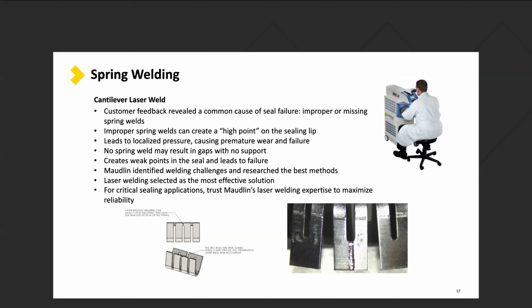A couple things can happen. If you overlap the springs, you get a high point, that's going to cause the seal to wear prematurely at that high point. So if the spring overlap is causing a lump in the seal jacket, we've seen that quite a bit. In terms of failure mode, we've also seen where the spring is cut too short by the customer and there's a gap, and that gap allows for the seal to be unsupported in that area, and you'll get a leak past that point.